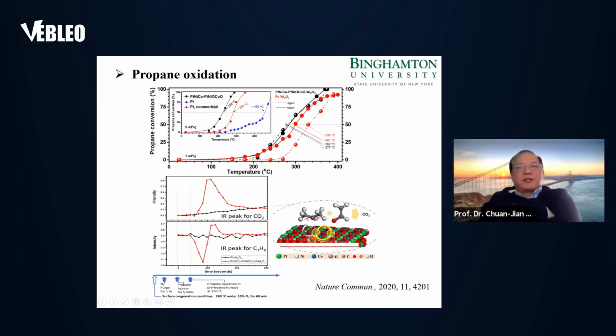One of the things is about oxygen, right? So what is the role of oxygen? In the lower panel of this slide, we try to illustrate this: if we first oxygenate the nanoparticles, then we introduce the propane without introducing oxygen, then we see the oxidation of propane. So the only source of oxygen is coming from the lattice oxygen, the surface or lattice oxygen, as illustrated on the right-hand side. The red atoms are the oxygen species in the surface of the lattice. This demonstrates that the surface of the oxygenated nanoparticles plays a major role in the catalytic oxidation reaction. That's unique for the ternary nanoparticles.